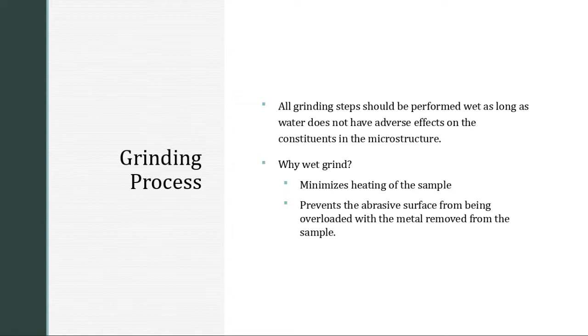The other reason you wet grind is to prevent the abrasives on the surface from being overloaded. As you remove metal, that metal stays on the pad, and if your metal overloads that pad, you're no longer abrading the surface, and instead you can create an issue with material being smeared back onto your sample. So the wet grinding process helps remove the particulates being abraded off the pad, revealing still fresh abrasive for the cutting surface.